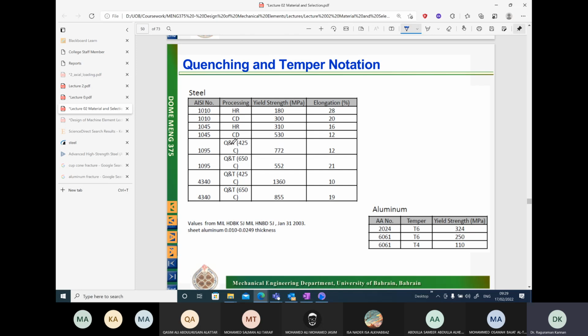You can see here we do quenching and tempering operation, and the tempering temperature is 425 degrees, 650 here. So depending upon tempering temperature, you can see difference in properties. 4340 steel is one of the strongest materials, highest strength material, and you can see yield strength goes to nearly gigapascals or more. Again, depending upon quenching and tempering operation, you have different properties. This is the effect of heat treatment: significant increase or significant reduction in the yield strength of the material.